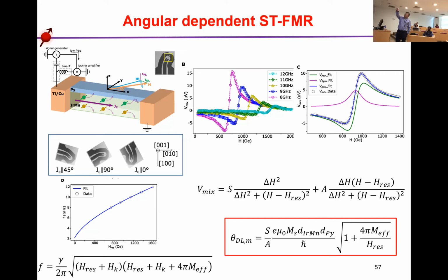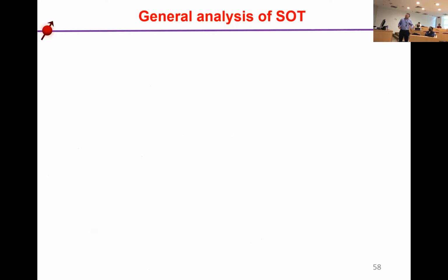So from here, we can say this spectrum will decompose into a symmetric part and an asymmetric part. The symmetric part corresponds to the damping-like torque. The asymmetric part corresponds to the field-like torque. So based on this, you can calculate the SOT efficiency. And in order to get a large signal, we apply the magnetic field along the 45 degree, which is the highest AMR effect. For the angular dependence, we change the magnetization, changing the magnetic field along the in-plane directions. So definitely we need to derive how the voltage changes with the field directions.